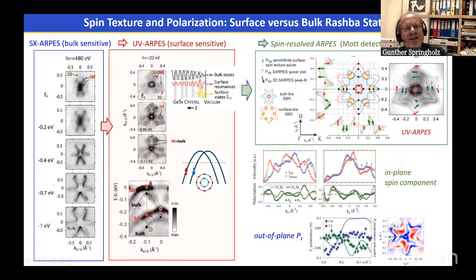The problem with that is that at low photon energies in the UV range, ARPES becomes very surface sensitive, and for most systems, there are surface resonance states or even surface states formed at the surface of most materials. That means that in this UV ARPES range, the bulk band structure is superimposed by a surface band structure, and one can see this difference here by comparing these two images. So in the UV range, we observe these star-shaped bands superimposed on, or in addition to, the bulk bands.